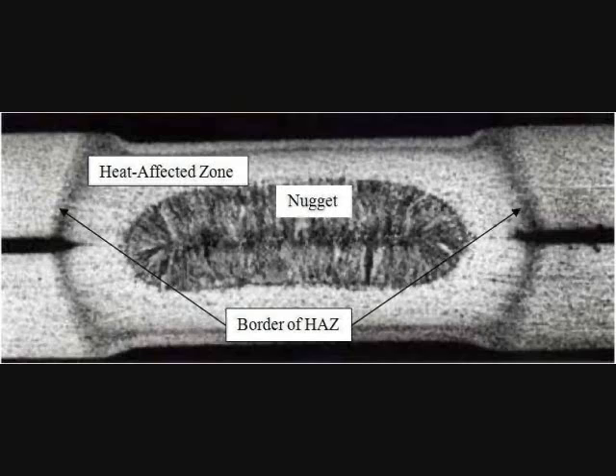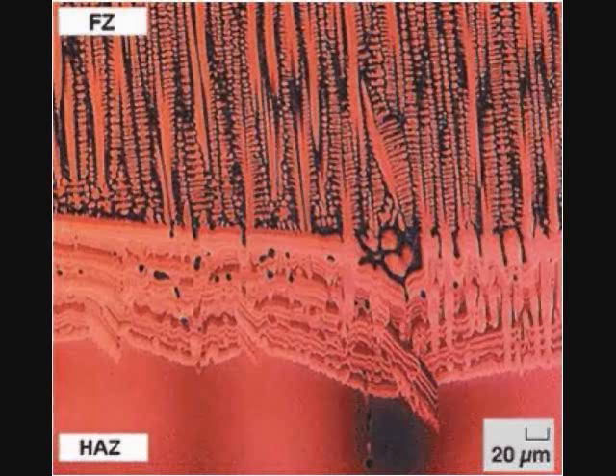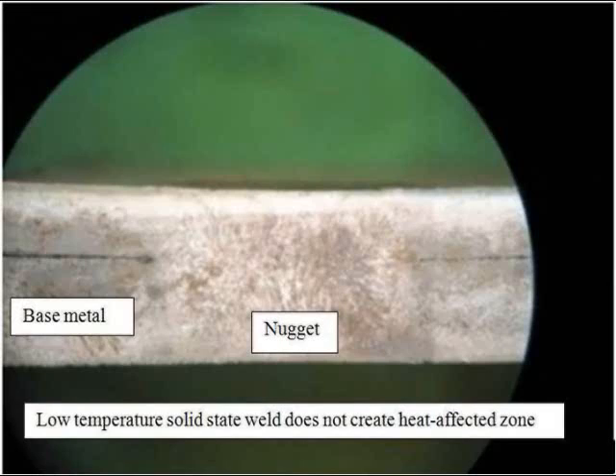And the nugget itself, because it heated up to high temperature, then recrystallized. So you can see a lot of dendrite. This is a picture of the dendrite, except it's amplified a little bit closer. And we can see the FZ, which is the fusion zone. HAZ is the heat affected zone. And you see the corner, there's 20 micrometer how wide it is. This is a low temperature solid state weld. You can clearly see the interface, there's no line. And on both sides, the metal looks the same.